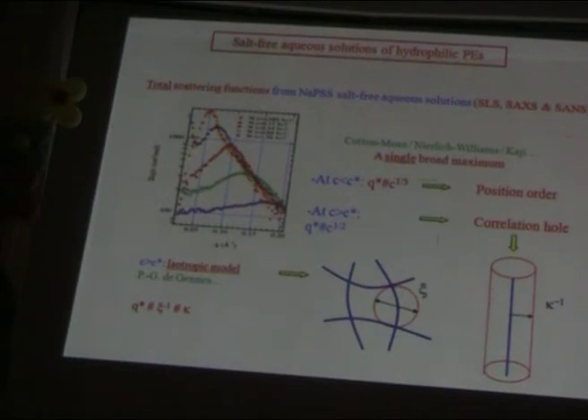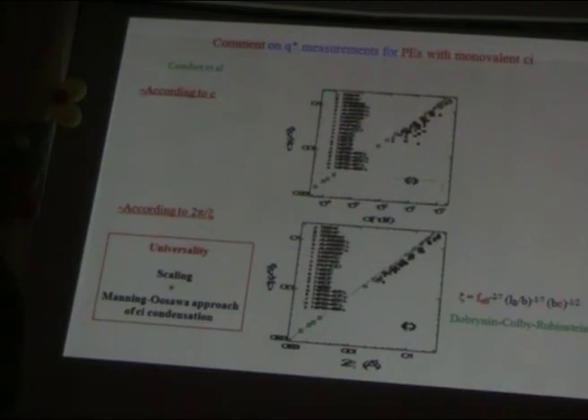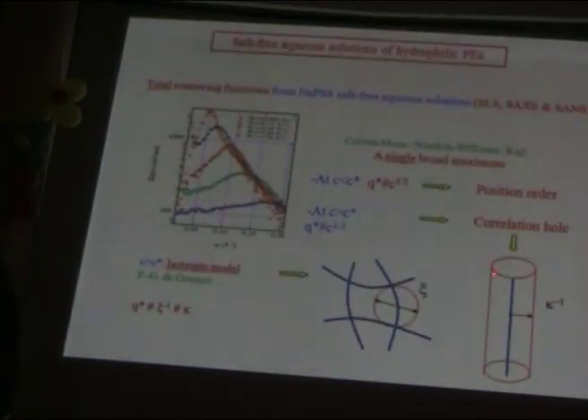If you put hard spheres, you have a peak when you increase the concentration, but this peak does not move because it's related to a correlation hole. But in the case of the polyelectrolyte, the volume of this correlation hole depends on the concentration. Why? Because it depends on the ionic strength, on the Debye screening length. So when you change the concentration, you change the position, because the volume of the correlation hole changes with the concentration via the Debye screening length. So you see you have a peak, but you have no translation order, no orientation order. You have a perfectly disordered system.